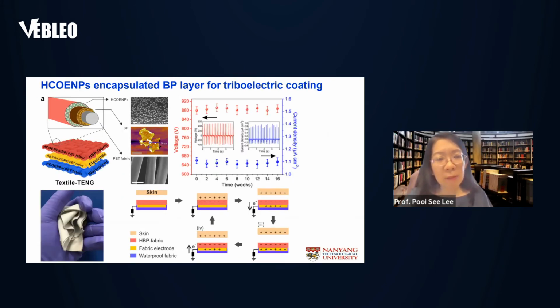So this bilayer structure can be introduced onto textile wearable devices in order to fabricate a textile energy harvester based on a triboelectric mechanism. In the triboelectric mechanism, it is based on the charge harvesting from the surface through a contact mode, frictional mode, or sliding mode. So in this example, it is by compression mode. And the use of the black phosphorus as the charge trapping layer has enhanced the charge density that is incurred during the contact mode, which leads to a high voltage output as a function of time. It also shows very good durability.